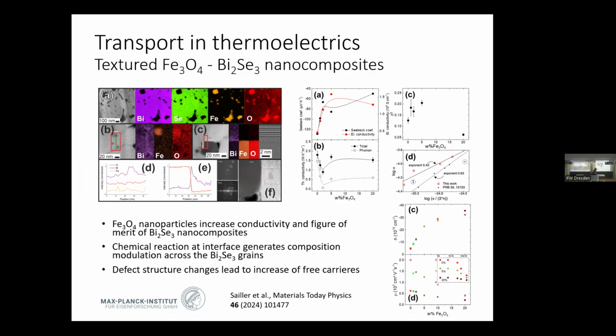The more iron oxide we put into it, the localization changes from weak anti-localization to weak localization, in terms of the shape of it. What they would say is that the spin-orbit constant changes from positive to negative. And that points to a certain interaction from a magnetic component to something close to the surface, close to that area, but properties of the bulk of the material.